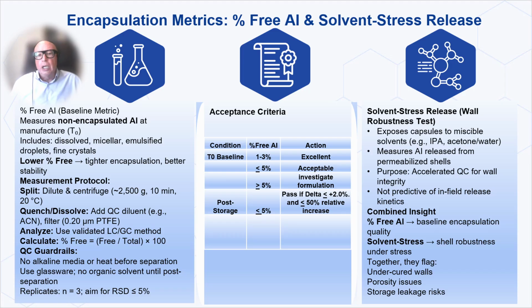Solvent stress release test. This tests wall robustness by exposing capsules to miscible solvents like IPA and acetone water. We measure AI released from stressed capsule walls. It's for evaluation of wall integrity, not predicting release kinetics. Together, free AI shows baseline encapsulation quality, while solvent stress shows shell robustness. They help identify undercured walls, porosity issues, and storage leakage risks.